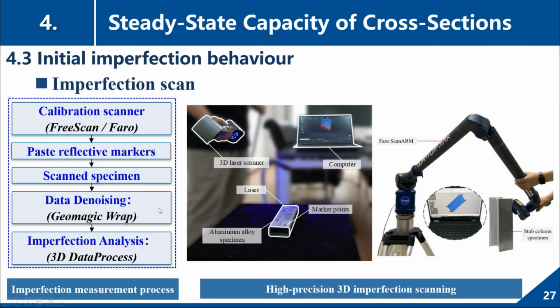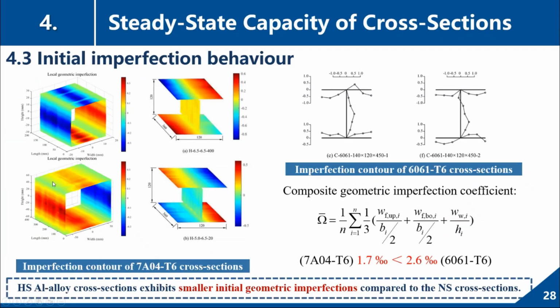Before the test, we scanned the imperfection of all of the specimens by scanner. And then we processed the data through the software of Geomagic Wrap. And we found that the high-strength aluminum alloy cross-sections exhibit smaller initial geometric imperfections compared to the normal strength cross-sections due to its strength advantage. During the transportation and fabrication, the high strength makes it less possible to deform, so with lower imperfection.